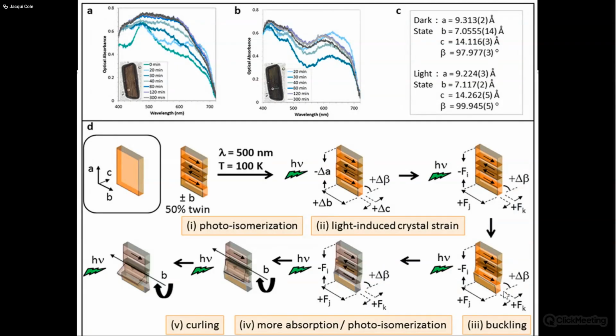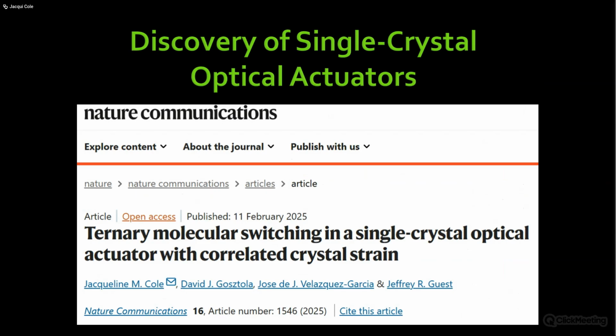And so it seems that the crystal, as far as I can work it out, seems to buckle, and because you've got the domains from the twinning, that's okay, and it's consistent with beta, because that's the beta which is the biggest change, right? And then, having buckled, you keep applying light, and it would eventually, I guess, peel, right? I mean, it's a sort of cartoon, but it's our best understanding of what's happening at this stage.